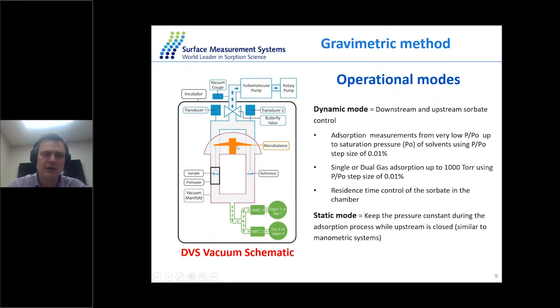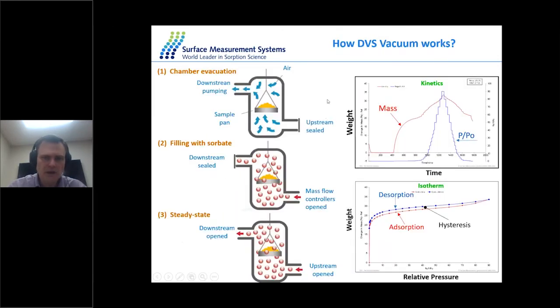While the balance is continuously measuring the changes in the mass. Now, how does a typical experiment actually work? First, you load the sample. This can be pellets, beads, or powders. The sample is loaded in this metal pan, which is suspended on a wire hanging down from the balance beam. At this stage, we close the chamber and pull high vacuum. During this stage, we are going to outgas the material.